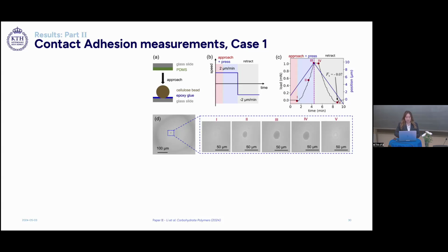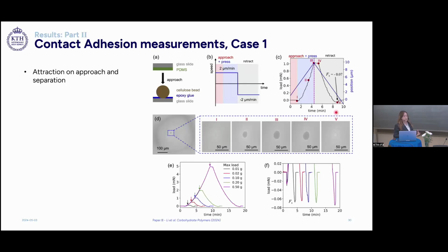So, starting with case 1, where we have a cellulose bead measured against a PDMS film, we can see from the loading and unloading curves here that there's attraction on approach and on separation, where the surfaces jump into contact, and then when separated, we have a pull-off force. This pull-off force is connected to the contact area, which can be monitored using an optical microscope throughout the whole measurement. And when we increase the trigger load, we can see that the pull-off force remains almost constant. And this means that it's independent from the applied load in this case.